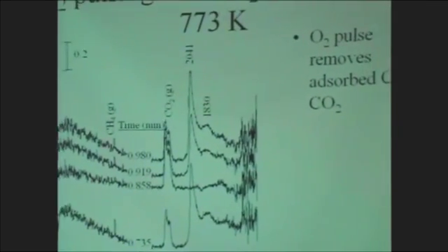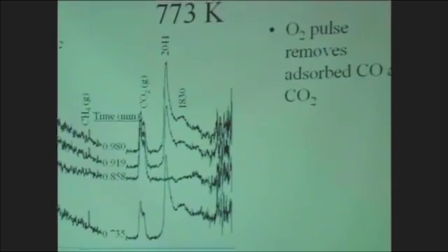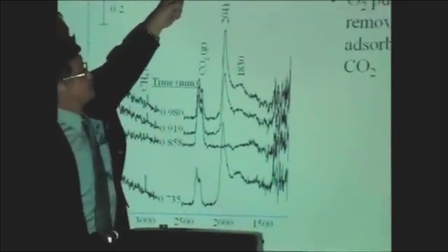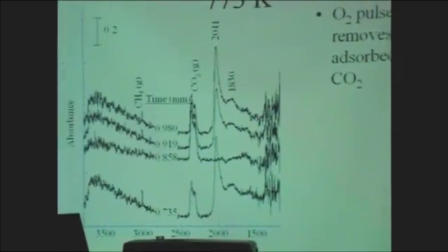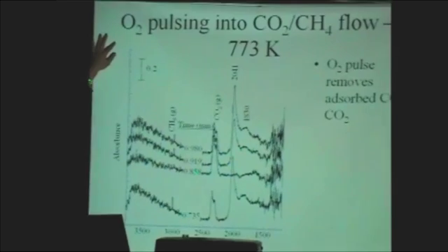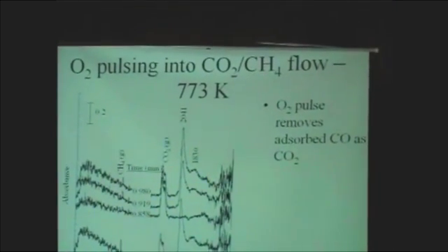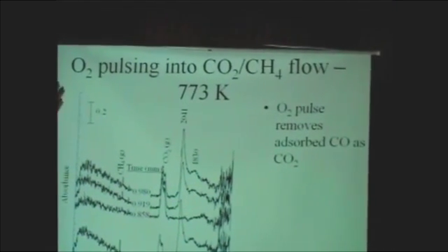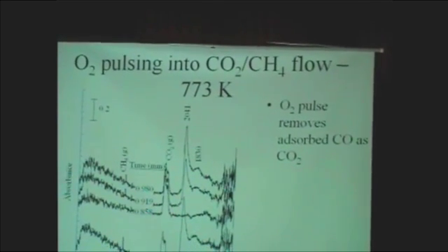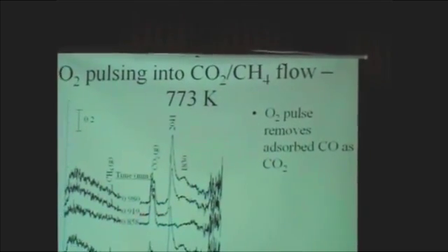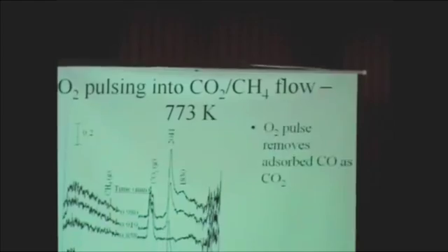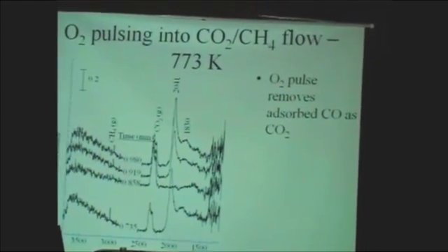But it's so hard to control the oxygen into the reactor because the flow rate we run in this reaction is CO2 and methane. The flow rate is 15 cc per minute of CO2, 15 cc per minute of methane. And if we want to send 2 cc per minute of oxygen in, it's very difficult because 2 cc per minute is really the lower limit of our mass flow meter. So we cannot send a small amount of oxygen in there. And the oxygen tends to oxidize the filament of the mass flow meter, so the filament tends to be burned out by this oxygen.